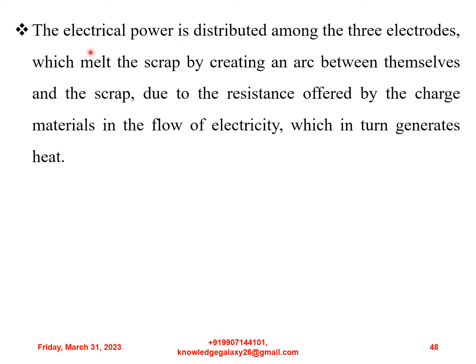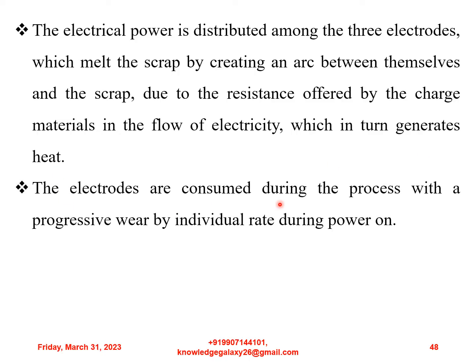The electrical power is distributed among the three electrodes, which melt the scrap by creating an arc between themselves and the scrap due to the resistance offered by the charged materials to the flow of electricity, which in turn generates heat. The electrodes are consumed during the process with a progressive wear at an individual rate during power on. Some adjustments of the electrode positions need to be done to make sure that all three electrodes are in contact with the material so that energy is efficiently transferred.